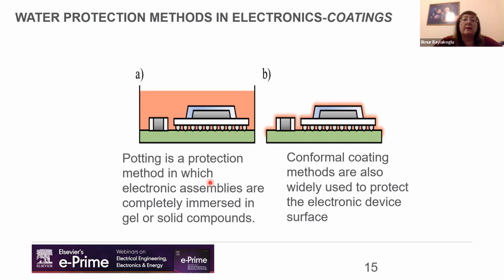Epoxy potting usually provides better adhesion to metals compared to urethane and silicone potting because epoxy resin mostly consists of various functional groups like ether, ester, amide, and amine. They can chelate metal atoms on the surface. However, epoxy materials are really hygroscopic. They attract and hold water. So because of their nature, they cause some other various failure modes with moisture. We are using something to protect, but it can cause other failures, which, of course, is a trade-off.